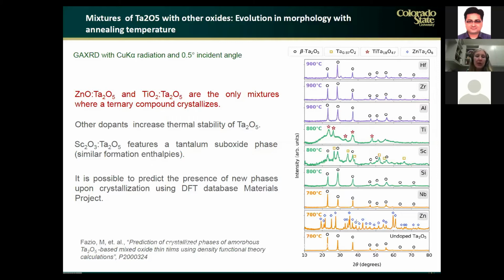One of the most recent works that one of the members of my group has done is actually to predict these new phases that appear upon crystallization using density functional theory with data that is on the Materials Project. So this is work that is in progress, but we were very pleased because this is the very first time that the Materials Project has been used for amorphous materials.